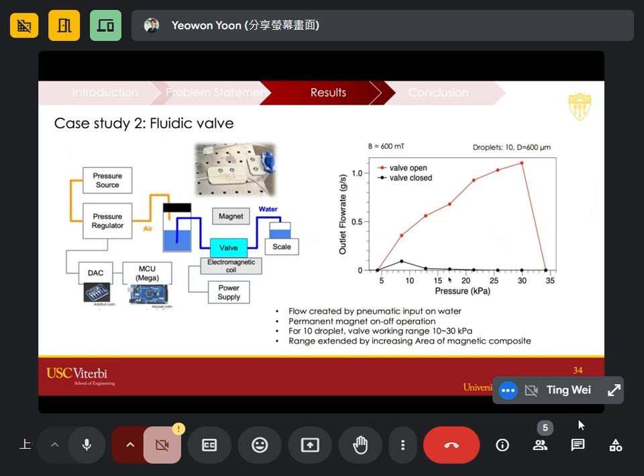So this is the layout of the experiment. You can see if the valve is open, it works at a certain point. Here we are able to achieve about 30 kilopascal. And then if the pressure becomes higher than that, this bending motion cannot actually overcome the pressure. It becomes a closed valve again. So we think this can work as some sort of safety valve. It only works in a certain range of pressure, and if it goes too high, the valve shuts off by itself.